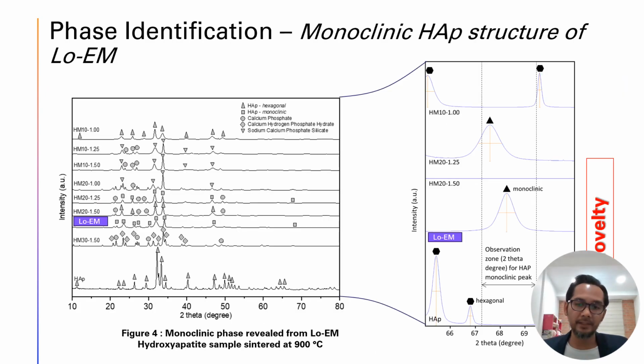Okay. So next, this is our novelty. We play around with the solid ratio of the hydroxyapatite plus metakaolin. We found that at 900 degrees Celsius, we are able to have HAP with the monoclinic structure. So how do we prove it? We deeply studied it with the X-ray diffraction technique. We found that at 68.3 there is a peak to confirm it is a monoclinic structure. So it's confirmed that at 900 degrees Celsius we have a single monoclinic phase structure for the hydroxyapatite. Okay.